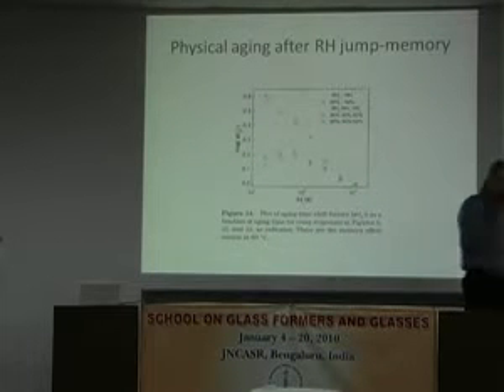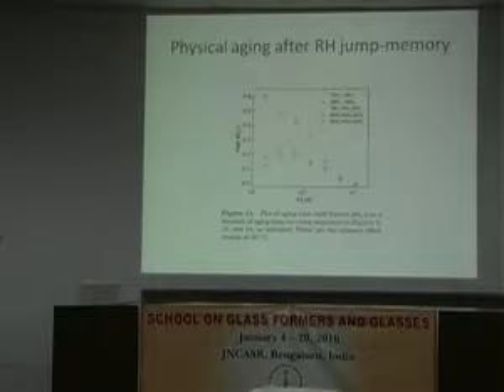So in the last lecture, what you showed were typically single time quantities. So you looked at the volume as a function of aging time. Right. So describe the Kovacs. Right. So here, instead of single time quantities, for each elapsed time, you're looking at a response curve. I'm looking at a relaxation time, right? Right. And so you're calculating a local relaxation time. Right. So it's the local relaxation time which you're characterizing with this shift factor A. That's right. In comparison with a reference relaxation. That's absolutely correct.